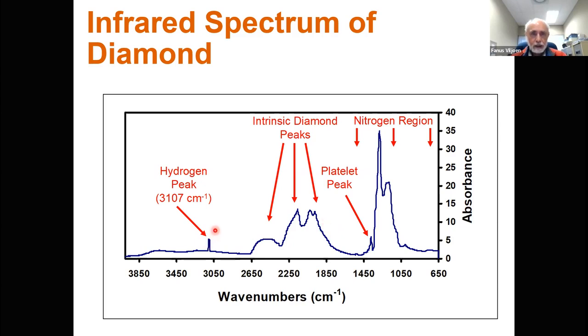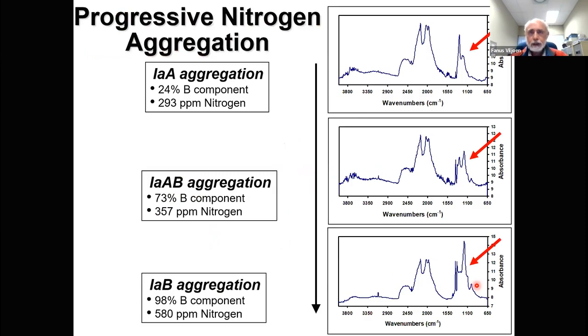Over here, some diamonds do contain hydrogen, and when they do, you have carbon-hydrogen vibrational bonds, which show up in this region of the infrared spectrum. Now, the nitrogen in diamond is originally captured as a carbon-nitrogen substitution. And that's very typical of diamonds that are very young, or for that matter, of diamonds that are synthetic in origin. Natural diamonds, because of the temperatures in the mantle and because of the mobility of nitrogen through the crystal lattice at high temperature, along with time, result in a different type of aggregation of nitrogen. And so, for example, a diamond that has crystallized fairly recently at high temperature and has had a little bit of time for the nitrogen to aggregate would have an infrared spectrum that looks like this.